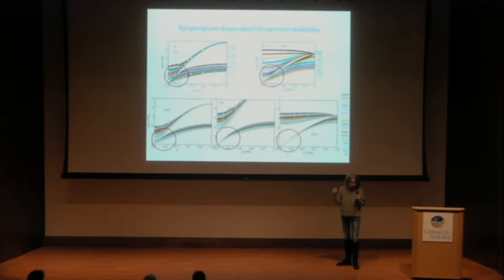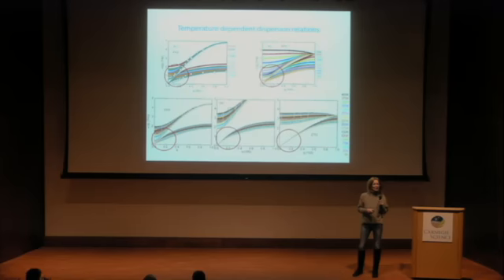Now I come to the dispersion of all these compounds, and you see striking differences in these dispersions. So this is lead titanate. I put in some experimental points, and you see the softening of the optic mode and the simultaneous one of the acoustic mode, which I just plotted in the slide before. What is really striking is lead barium titanate. You see that it is almost dispersion-free, the optic mode at high temperature, and only gains dispersion if you go to lower temperature. Strontium titanate looks well behaved, the same as calcium titanate, and what is different again is europium titanate.